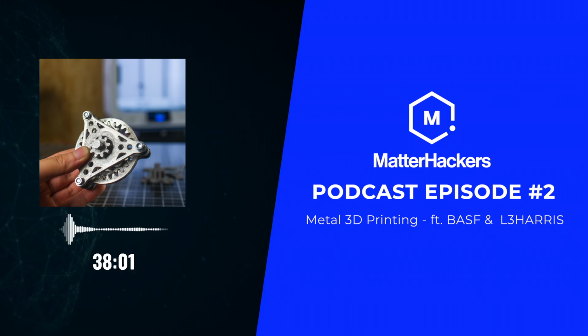Here's an example of another little part. This one's used to hold an electronic component with wires on it off of the circuit board when it's installed. You'll see in the design model a slot in there. We actually removed that slot when we printed this part. We added a raft around it just to make sure everything was flat on the table. And then you'll see the printed green part with the raft removed, and then the sintered dense part after sintering. Again, the material cost was cheap, $20, 3 hours to make 4 of them. And of course, we paid $80 to get it sintered.